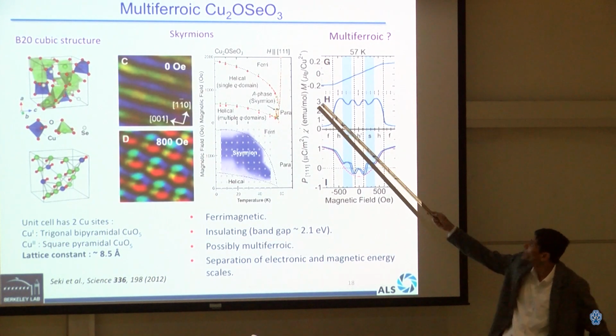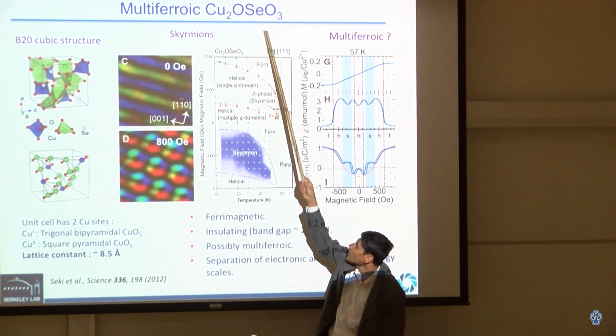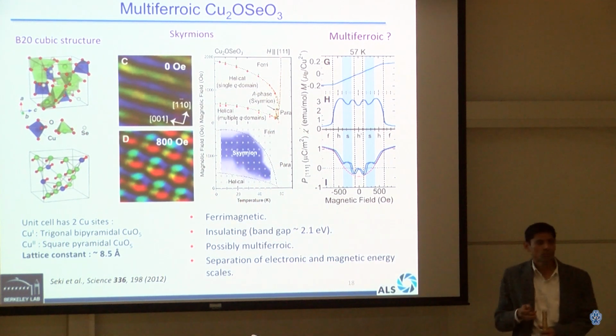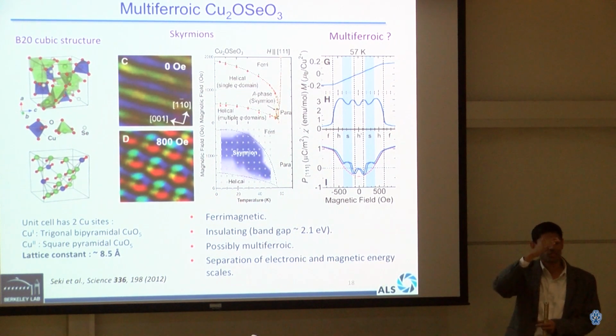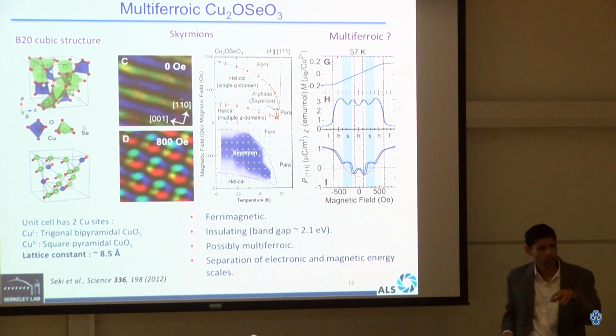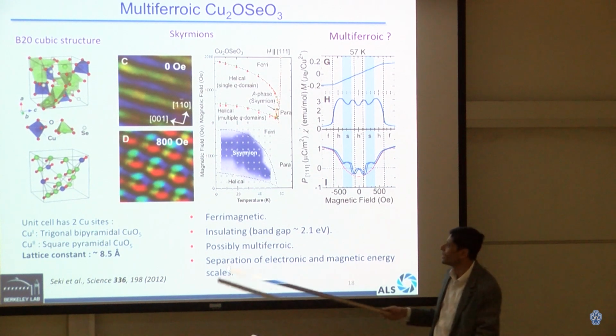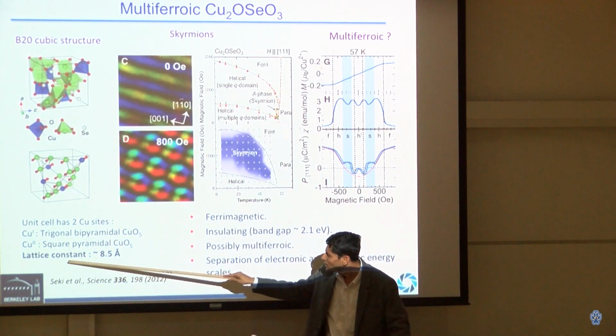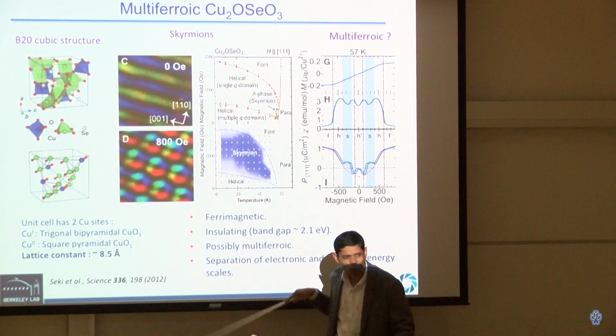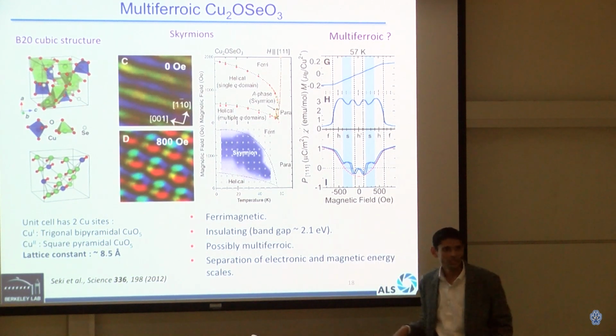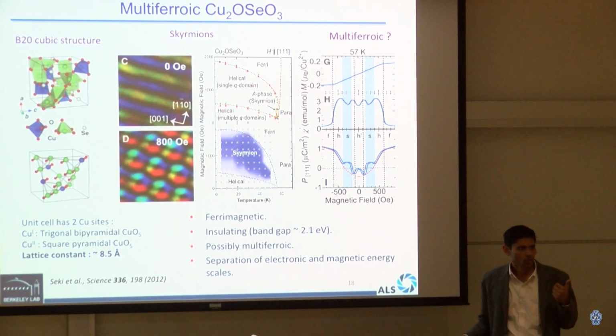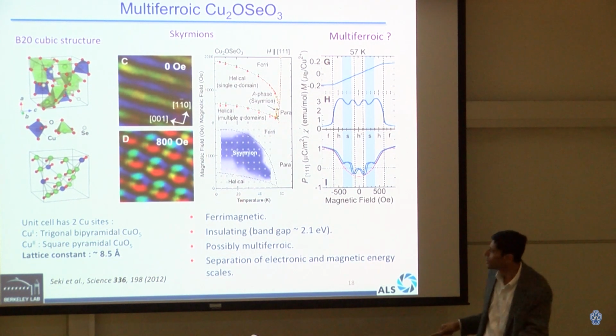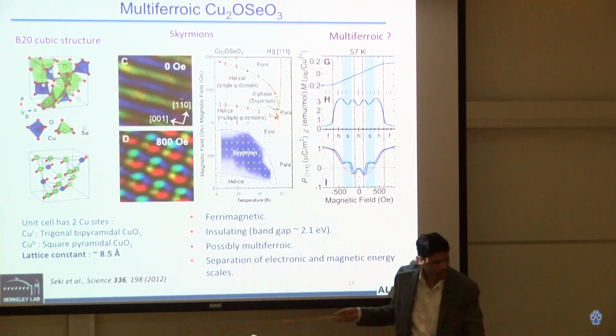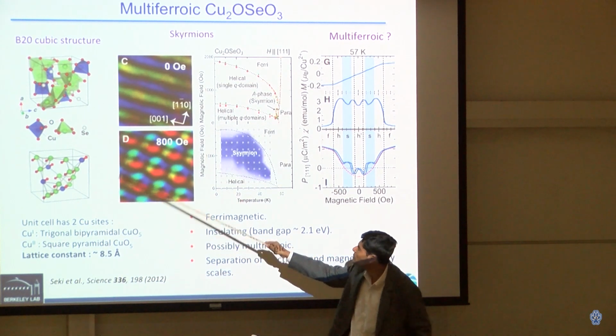And then we found this paper on copper oxide selenium oxide, which is a multiferroic, meaning that if you apply an electric field, its magnetic property changes, and if you apply a magnetic field, its electrical property changes. So that's why it's a multiferroic. The orders are coupled. And the big thing to see here is the lattice constant C of 8.5 angstrom. This comes to your point that we are using soft X-rays, whose wavelength is very large for us. So we could now access the lattice Bragg peak of this material.